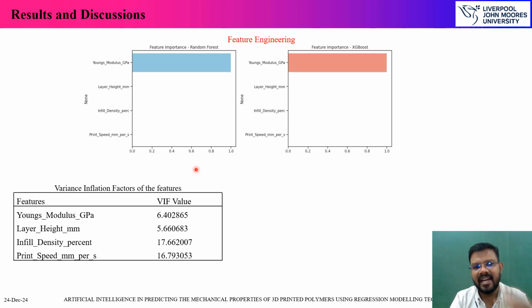To do that, we have the variance inflation factor value, which is determined as 6.4028 for Young's modulus, a layer height with a value of 5.66, infill density of 17.6, and then the print speed, which is measured as 16.8 units. However, from the thumb rule, any factor which is contributing a VIF greater than 5 has the least contribution or it could be eliminated. So this is what the VIF purpose is.